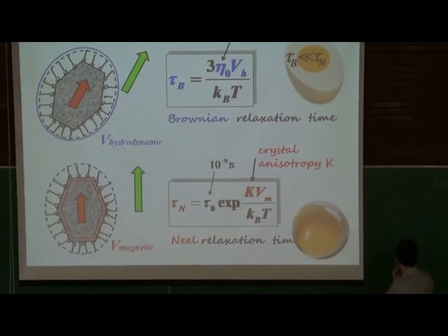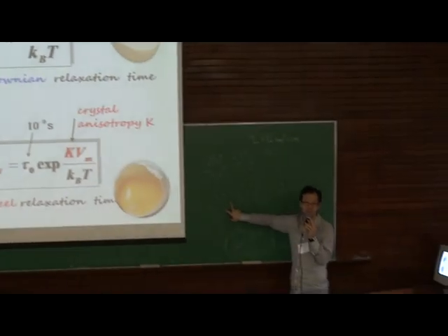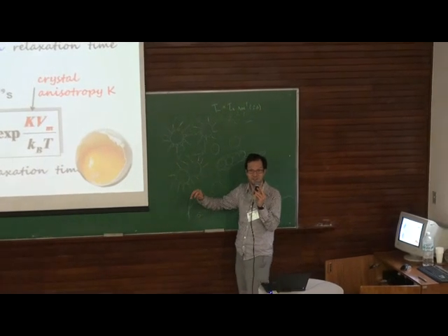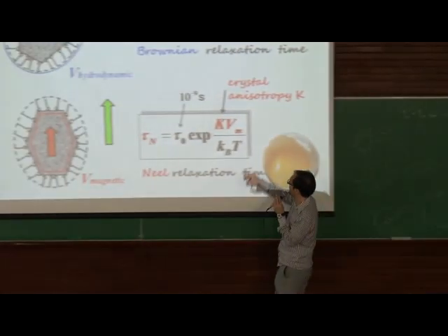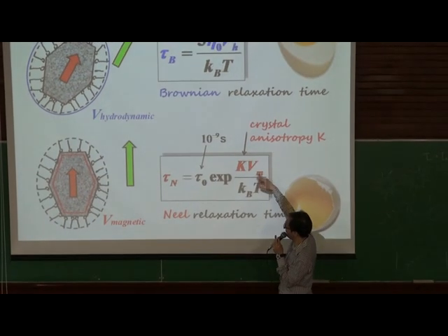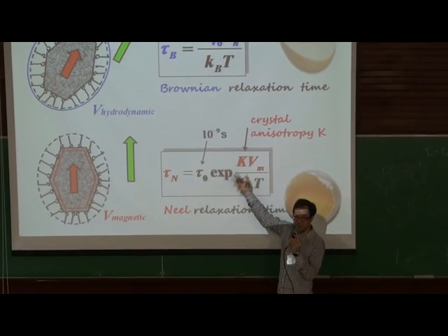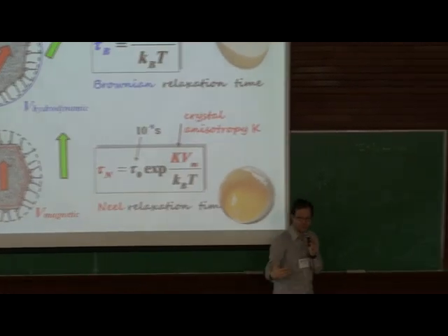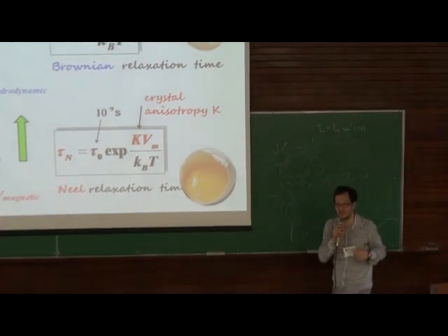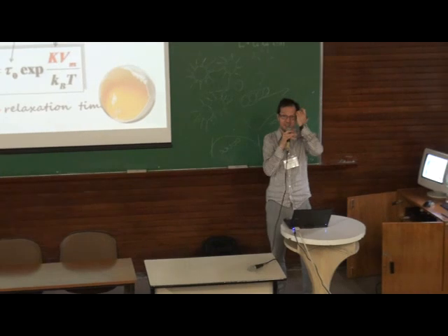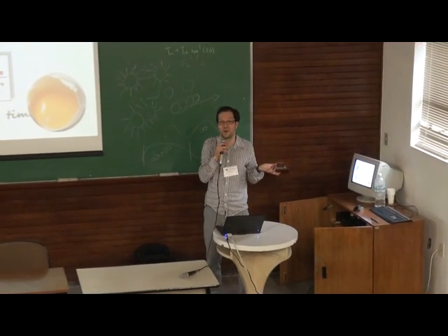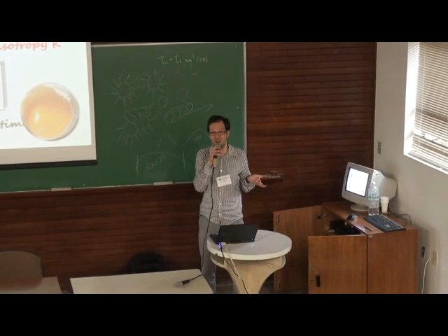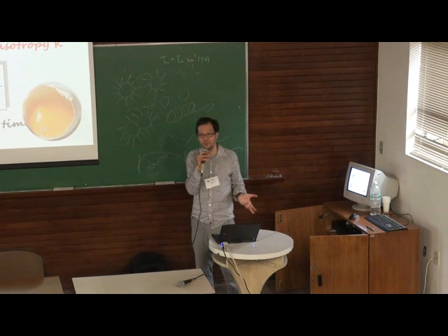But the combination of two of these guys to a primary agglomerate is then so large that you have a larger magnetic volume and you are over this exponential. I mean, you are already over 1 here, and then you contribute a lot. And this makes it so difficult with this microscopic description, especially with water-based ferrofluids, because they tend to agglomerate.